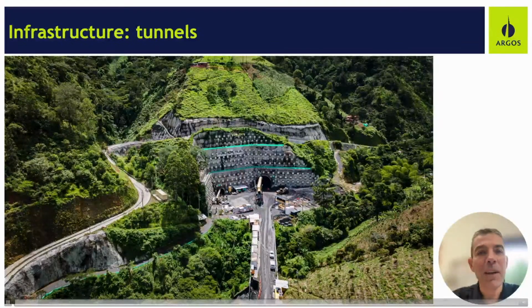The limestone calcined clay cement of the Rio Claro plant in Colombia has been used widely for the 4th generation concession roads program in Colombia. Here you see an application of a tunnel. So this product was used all the way through the tunnel, in the works that you see at the entrance and the exit of the tunnel, and also in the shotcretes and the paving and all the different construction elements that this tunnel had.